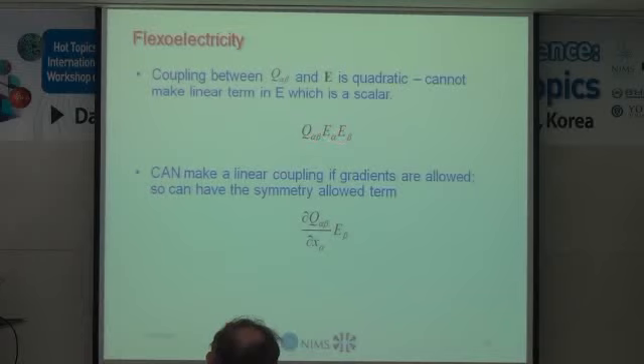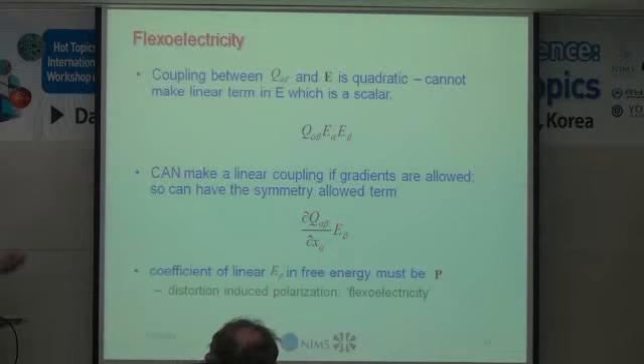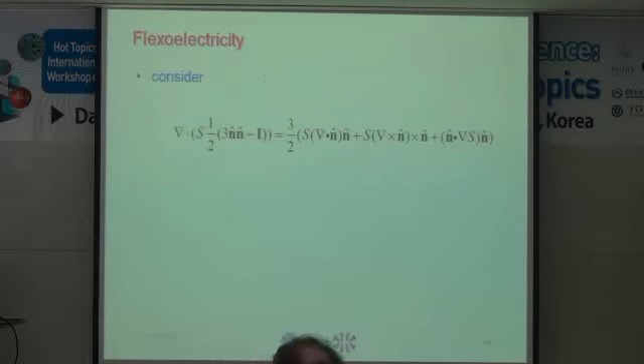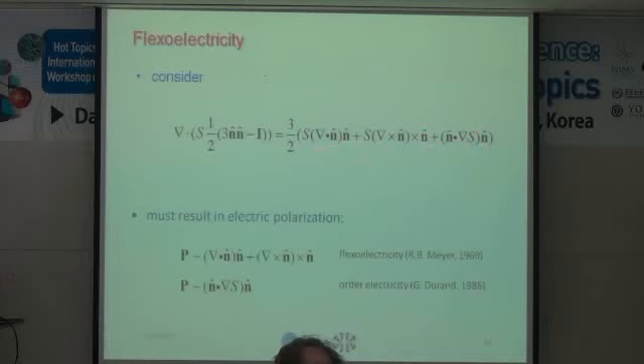So if you have a derivative, if you have the divergence of Q, that's a vector which you can dot with the electric field. So this is now an allowed scalar. And essentially, in a free energy, the coefficient of a linear term in E must be electric polarization. And so this means that if we have a spatially varying Q, we must have electric polarization. And if you write Q in this way, again as the scalar value and the director, and you take the divergence, you get three terms, and two of these are called the flexoelectric terms, proposed by Bob Meyer.